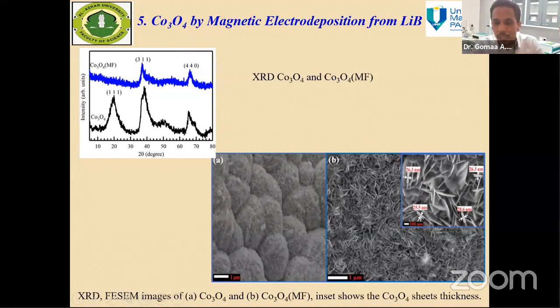So that is a combination of applying electrical power with magnetic power. Our aim in using magnetic power is to make alignment for the cobalt species. As we know, cobalt oxide has magnetic properties. So using the electrodeposition technique, it could be precipitated, but maybe in a random manner. So applying additive magnetic power could make the cobalt species precipitate on the substrate in a good manner. And we successfully got this, as the cobalt species precipitated in the form of nanosheet structure, compared to without magnetic power, where it just precipitated randomly as spheres.